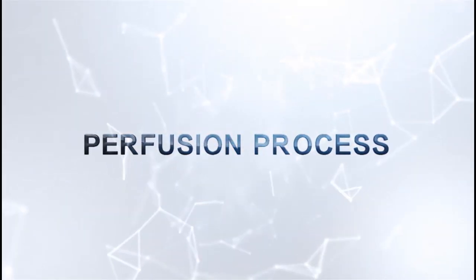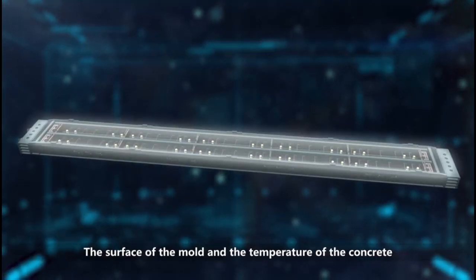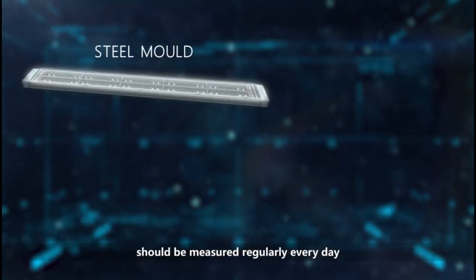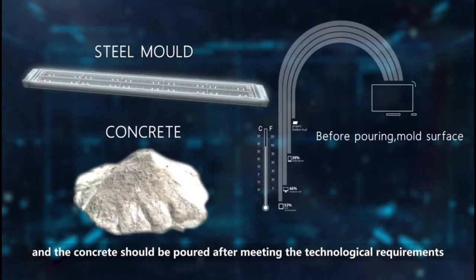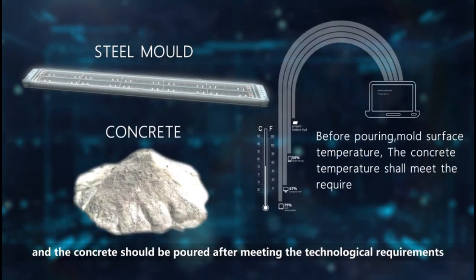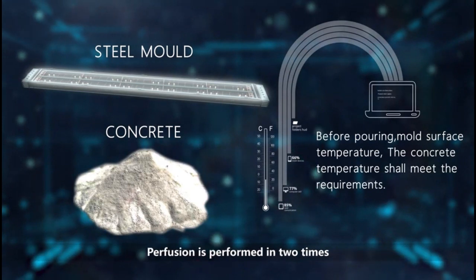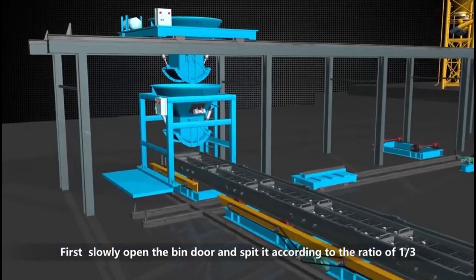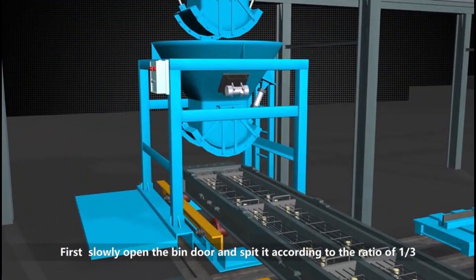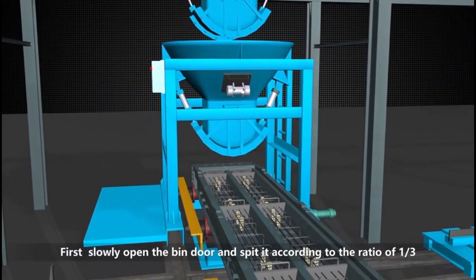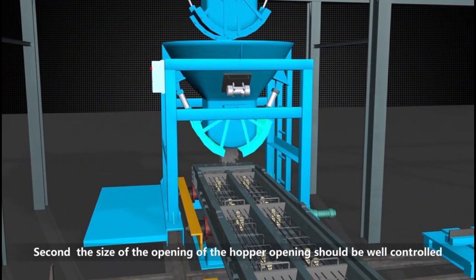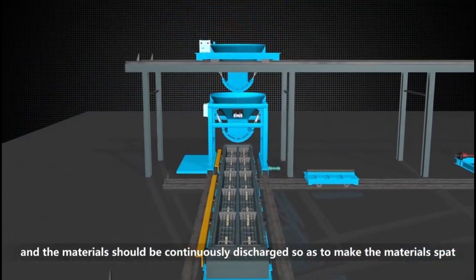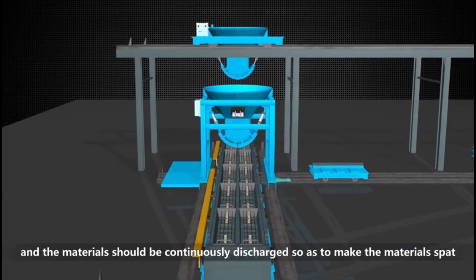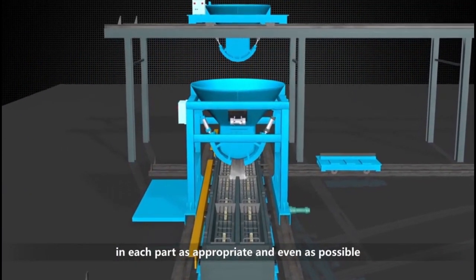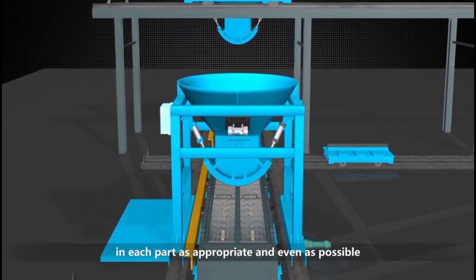Perfusion process. The surface of the mold and the temperature of the concrete shall be measured regularly every day, and the concrete shall be poured after meeting the technological requirement. Perfusion is performed in 2 times. First, slowly open the bin door and discharge according to the ratio of 1/3. Second, the size of the opening of the hopper opening shall be well controlled, and the materials should be continuously discharged so as to make the materials spread in each part as appropriate and even as possible.